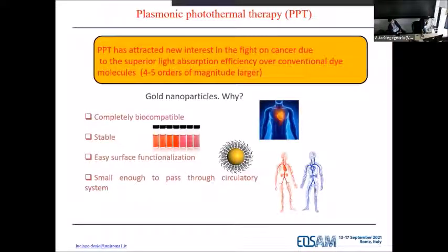So with this in mind, we had a big issue in the very beginning, which is related to the capping agent utilized for stabilizing golden nanoparticles. If you are familiar with chemistry, once you run the process to synthesize golden nanoparticles, it's mandatory, in order to have a stable colloidal solution like this, to have surface functionalization. This will avoid aggregation between particles, thus producing the so-called colloidal stability. And typically, the material we utilize for stabilizing is a very bad material with very high toxicity. This is the well-known CTAB, as an example. That's the beauty of those materials, but you cannot work with them because the toxicity is very high.